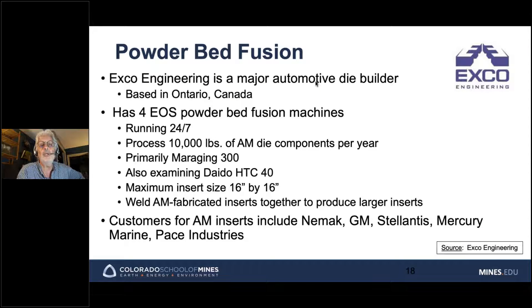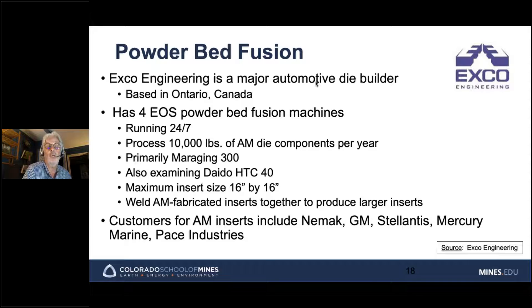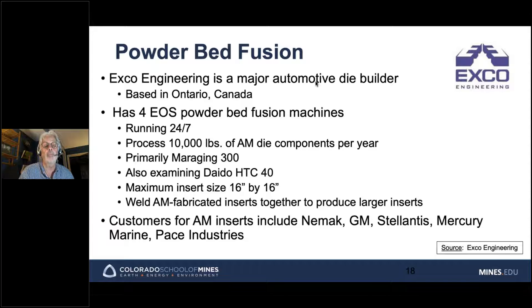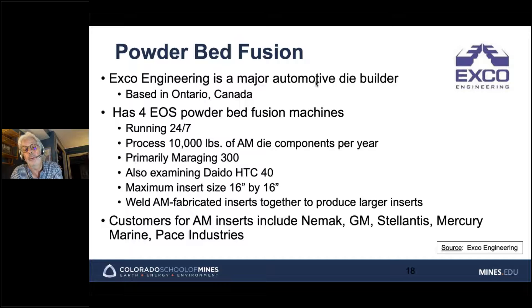Exco Engineering is a good example of powder bed fusion in action. They are a major automotive die builder in Ontario, Canada with four EOS powder bed fusion machines running basically 24/7, processing around 10,000 pounds per year of additive die components, primarily maraging 300 steel. They are just starting to examine a Daido steel grade called HTC 40, which is much more similar to H13 in composition. Their maximum size is 16 by 16 inches, but they produce larger inserts by welding additive parts together.